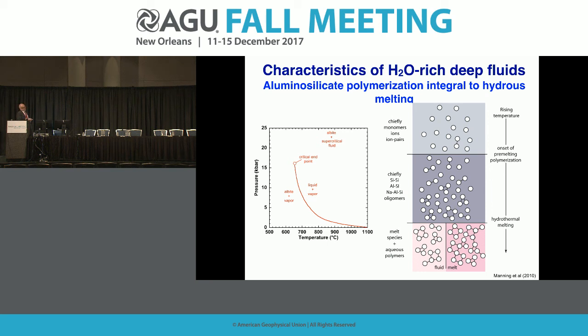In some sense, the aqueous phase is foretelling the onset of melting coming, say, 50 degrees C higher in temperature than the system might be at any given point, by the assembly of the constituents that will polymerize to form the silicate liquid in the aqueous phase. The chemistry in the aqueous phase is intimately linked with the melting process.